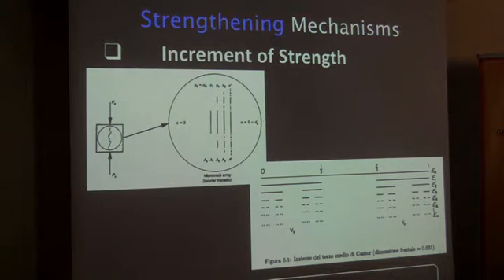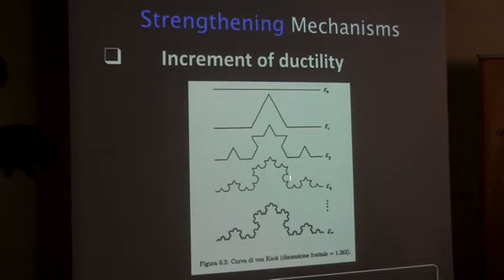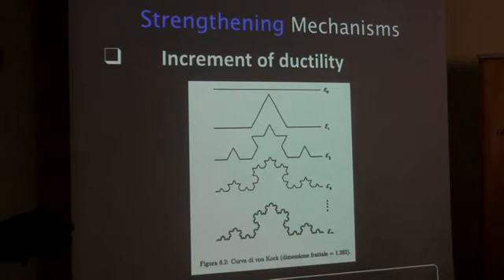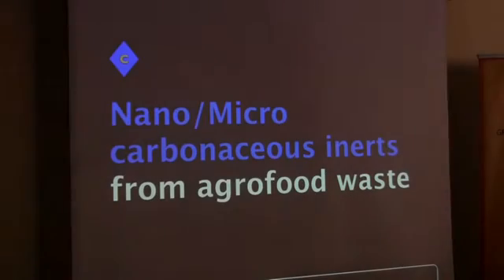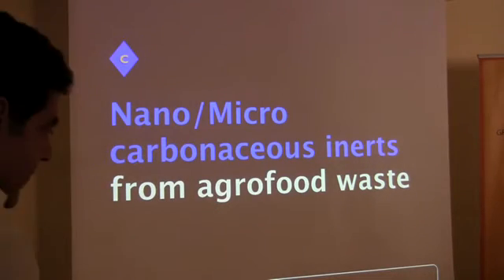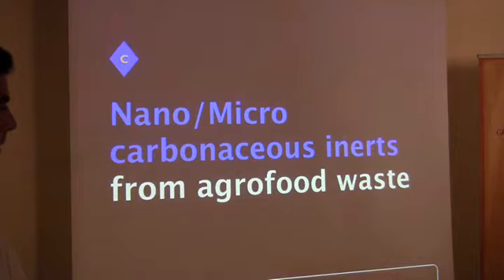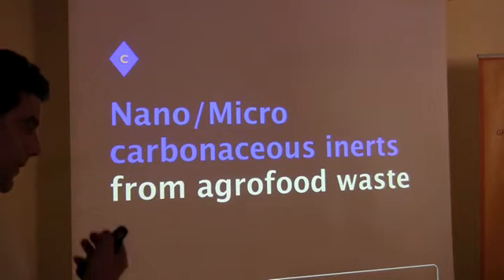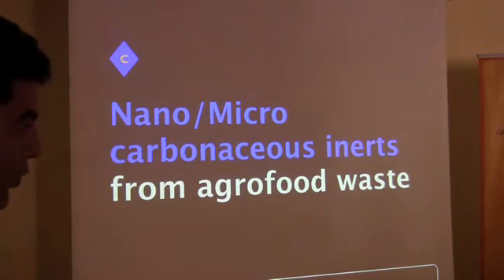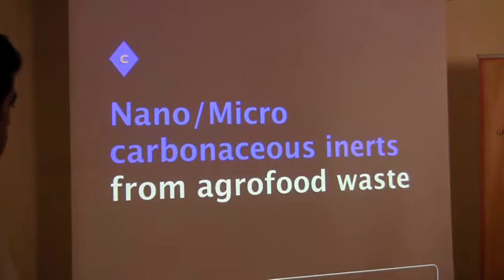In particular, what is interesting is that the strength increases because we are going to decrease the voids, the pores, and this is normal with respect to the silica fume addition. But also, we are going to increase the dimension of the fracture surface. The first idea that we had, of course, was that energy was expensive because we have to produce these carbonaceous inerts.